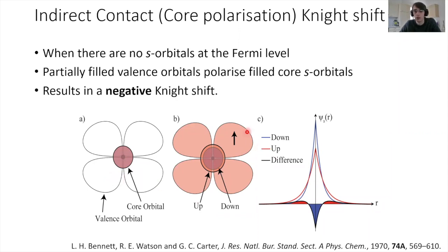Okay, now let's imagine we have some unpaired electron density in our valence orbital. I'm showing this for a d orbital here. Now our core up spin s orbital is going to expand into that space. That's because it's energetically favorable to do so via the exchange interaction, whereas our down spin orbital contracts for the opposite reason. So we still have the same amount of electron spin. This is a closed shell, completely filled s orbital. We've just changed its distribution. And if we plot that, in red is our up spin band that expands slightly, blue is our down spin band which contracts slightly, and we can see that the net effect is we have an excess of down spin at our nucleus, and that's what gives us that negative Knight shift.